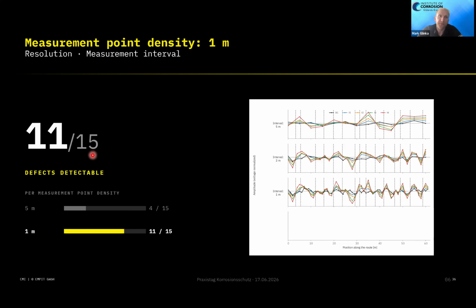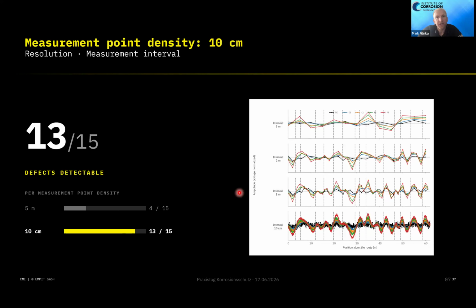When we are surveying with the interval of 1 meter, that becomes something we can rely on. So we are just missing, let's say, 15 to 20% of the defects. And if we then ramp it up to an interval of 10 centimeters, you can see that you then have a continuous signal and your curves look much more beautiful. You're detecting 13 out of 15 features.